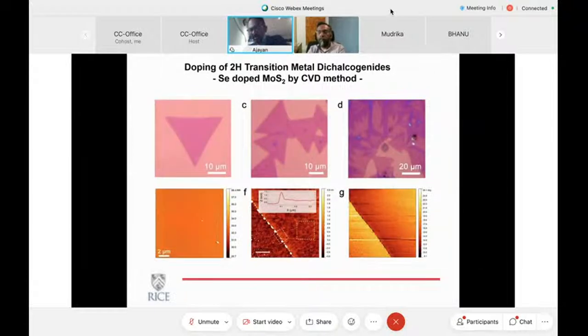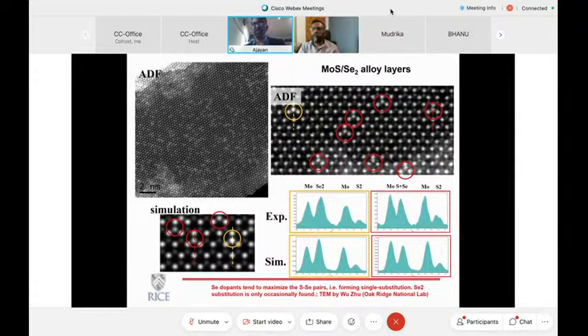The final piece that I will mention, maybe in the next 10 minutes or so, is related to doping and alloying and creating multi-component 2D layers. And unlike the carbon boron nitrogen system, where things get very segregated, we saw that when you start to put some dopants, particularly similar elements like selenium into molybdenum sulfide, or tellurium into molybdenum sulfide, or tungsten into molybdenum sulfide, they seem to distribute pretty well, at least at low dilutions and low concentrations. We did a lot of electron microscopy, STEM analysis, and so on to see how they distribute. And it looks like they are uniformly distributed.